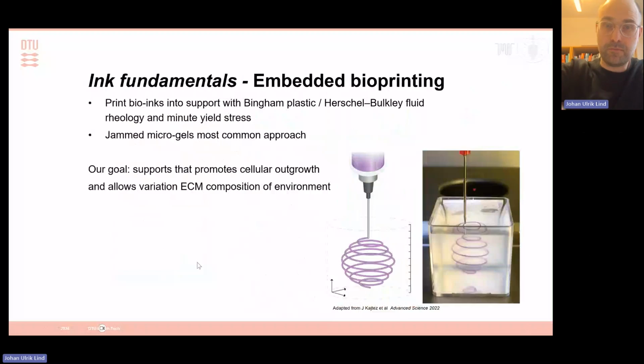Embedded printing is, of course, the most popular way to get around this. So you print into a support, and I would say the vast majority of studies in recent years has been on jammed microgels as a very biocompatible support for printing in your bioink. When we started looking at this, one of the things we were interested in is whether we can formulate supports that promote cellular outgrowth. One of the things that goes into that is, can you give a lot of space in this system? If you have jammed microgels and those gels are cross-linked, then you leave the cells with limited space for outgrowth. And the other thing we were interested in is whether we can make a system where we can vary the ECM composition that surrounds the cell quite easily.